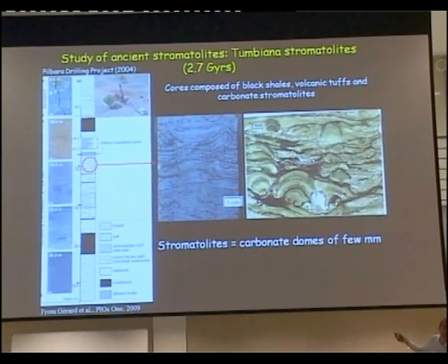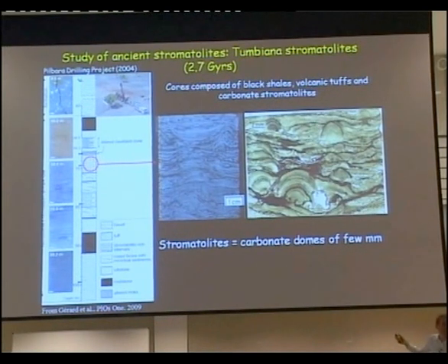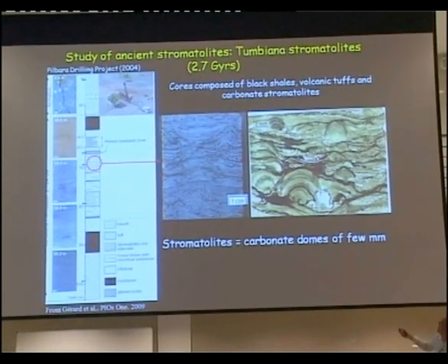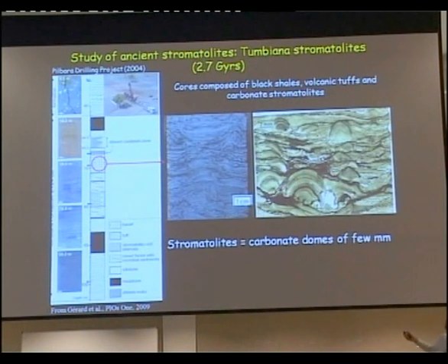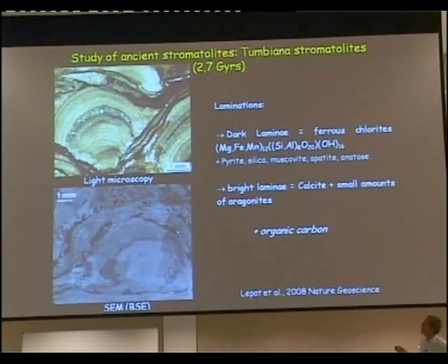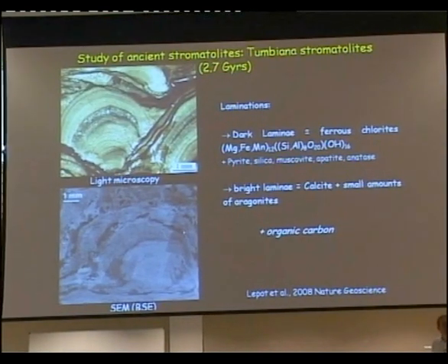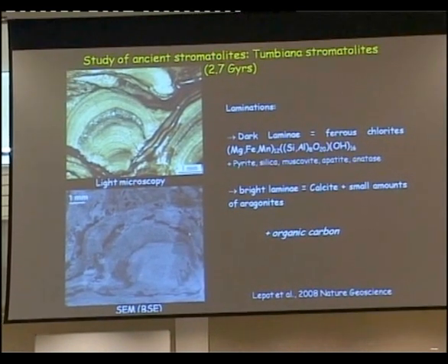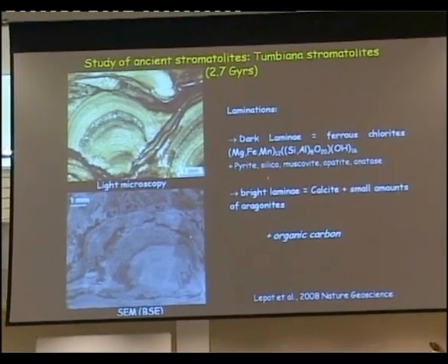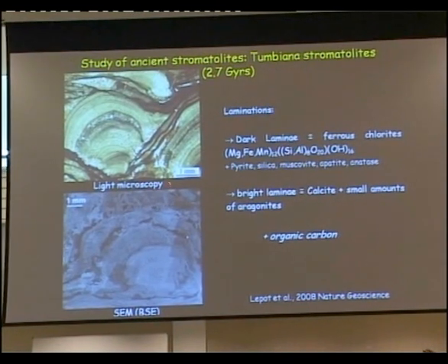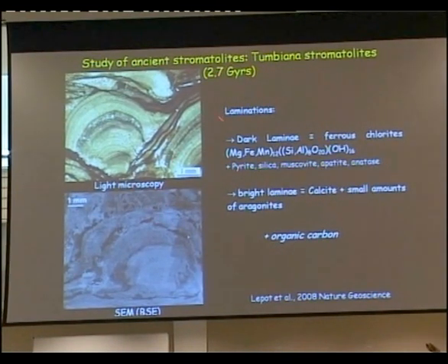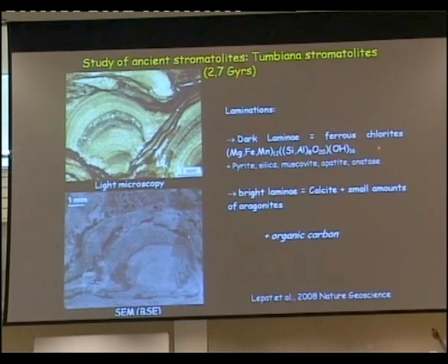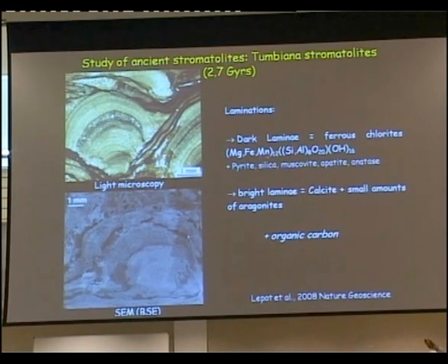You can already see that you have bright laminae, and you have dark laminae. So we studied it more carefully using scanning electron microscope, light microscopy, Raman spectroscopy. And basically what we could see is that the dark laminae are composed of ferrous chlorites. So they are, let's say, clays with magnesium, iron, and manganese.